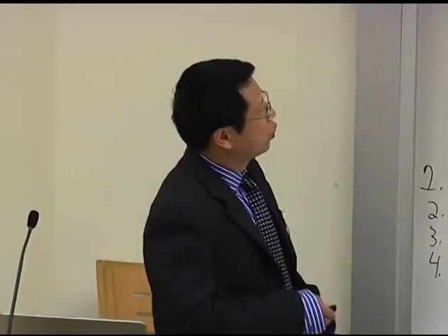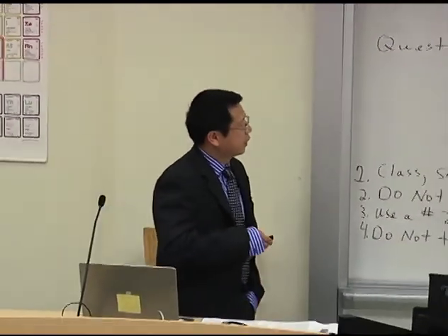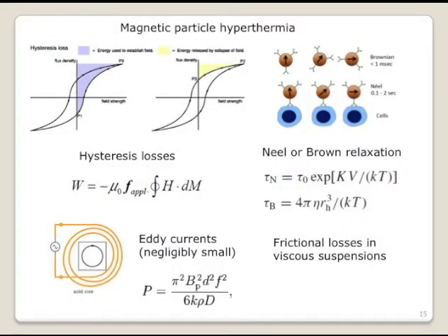And also we have the eddy current. Eddy current is due to the alternating electromagnetic field in a conducting material. We know the iron cobalt alloys are metallic, so they can also generate eddy current. But keep in mind, these nanoparticles are very tiny. Our nanoparticles are mostly below 10 nanometers, so the eddy current is negligibly small. So compared to the other 3 sources, this contribution to the heat generation can be neglected.